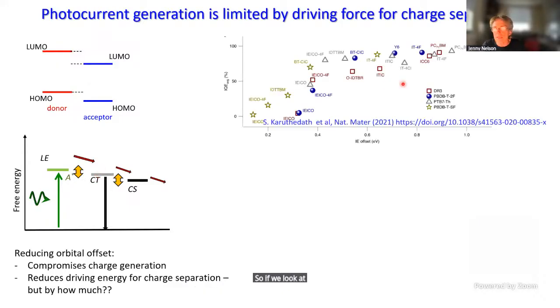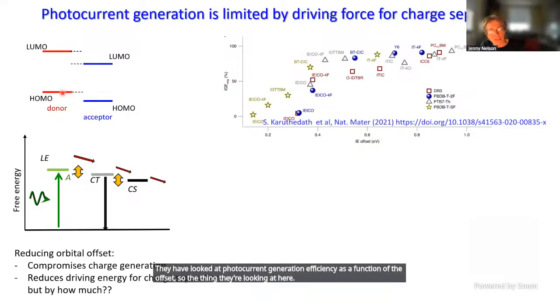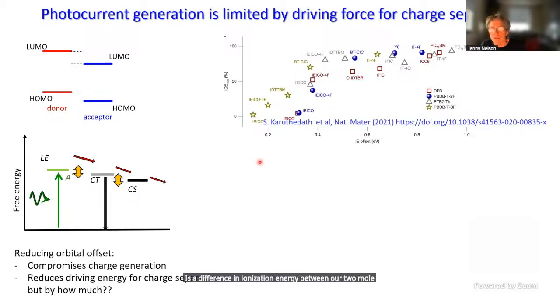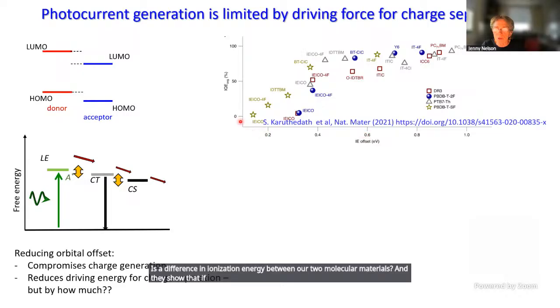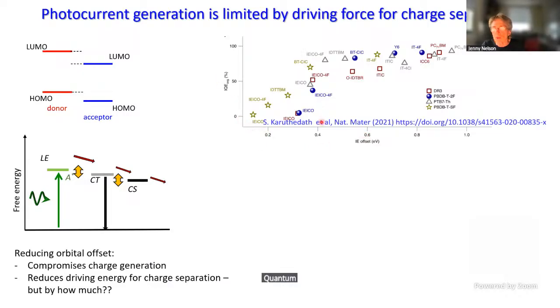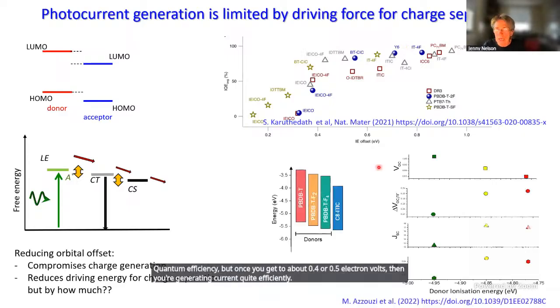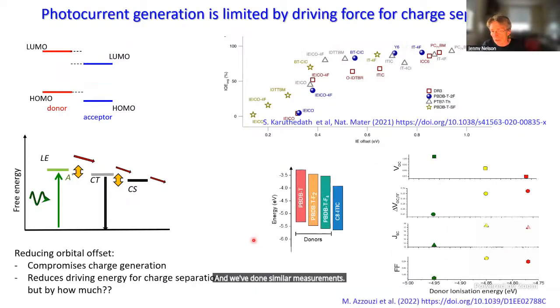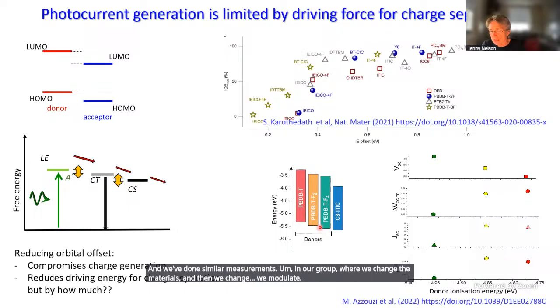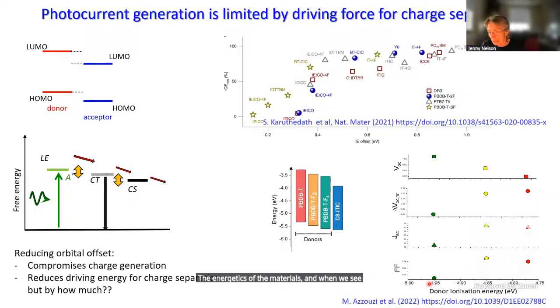So if we look at experimental data, this is from a paper that was published, they have looked at photocurrent generation efficiency as a function of the offset. So the thing they're looking at here is a difference in ionization energy between our two molecular materials. And they show that if that difference is too small, you don't get good photocurrent quantum efficiency. But once you get to about 0.4 or 0.5 electron volts, then you're generating current quite efficiently. And we've done similar measurements in our group, where we change the materials, and then we modulate the energetics of the materials. And we see that once our ionization energy gap is big enough, then we start to generate photocurrent efficiently. So that's nice.